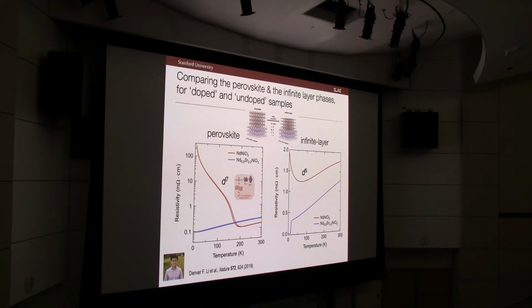This is a famous system for those in our community in that neodymium nickelate, for example, goes from a paramagnetic metal through a strong first order metal insulator transition associated with spin or orbital ordering. Okay? And if you hole dope the system, it turns out you suppress this metal insulator transition and you have something that looks nominally metallic all the way down.